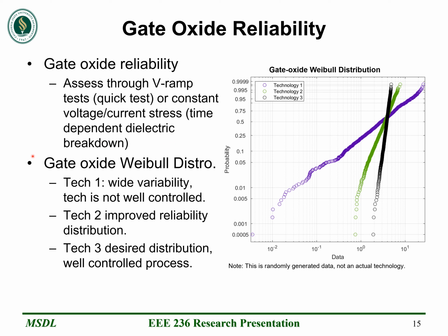So when we assess gate oxide reliability data, we typically take this failure data and plot it on a Weibull distribution. On the right, I have some fictitious data plotted on a Weibull plot. The data on the x-axis could be your breakdown voltage from your V-ramp test or your time to breakdown for your constant voltage stress. And on the y-axis is the Weibull probability. So for technology 1 in purple, you can see that there's a very wide variability. What this means is that the technology is not well controlled and the oxides break down at various different points along the x-axis.